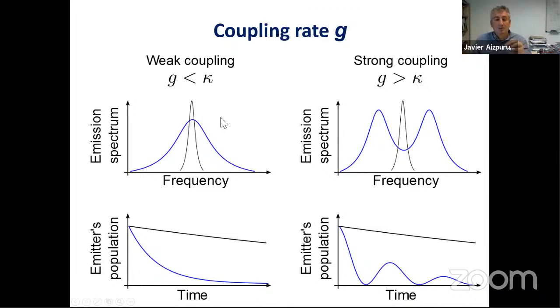So you see that in spectroscopy, the weak and the strong coupling regimes are very different: single peak, double peak, well distinguished. And in the time domain, in case one is able to do a pump and probe or a time domain spectroscopy of the population of the states, in the weak regime one would see an exponential accelerated decay of the exciton, and in the strong coupling case, you would see this Rabi oscillation, okay? So let me show you two examples of each.